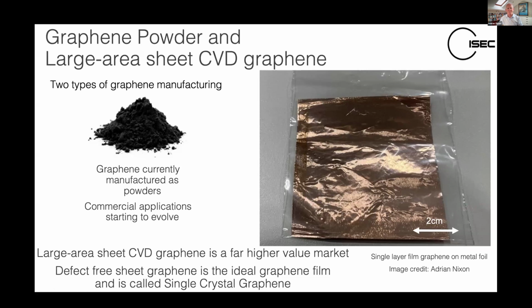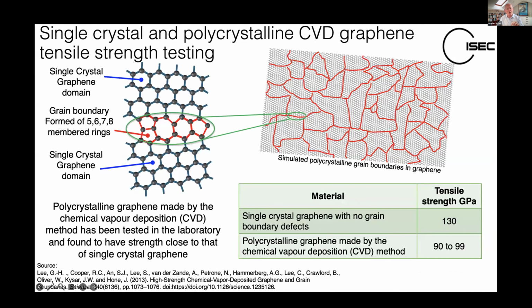More about that later. One other thing, graphene can also be classed as polycrystalline or crystalline. If it's single crystal, then the chicken wire pattern is uninterrupted across the entire boundary of the material. But there's also the term polycrystalline, which means that there are grain boundaries in here, and these are 5, 6, 7 membered rings, 8-membered rings sometimes. And you can see here that I've outlined these in red on the sheet.